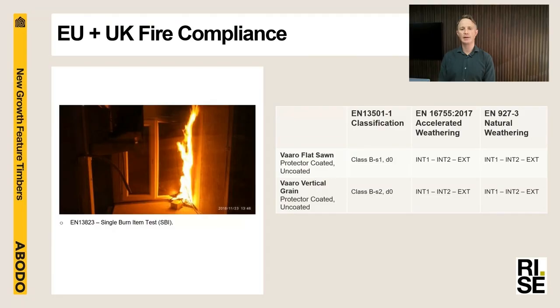For the EU and the UK, the EN 13823 single burn item test, or SBI test, was used. This is a slightly smaller scale test, 1.2 metre high wall in a corner configuration. And through this testing, we achieved Class B according to EN 13501, which is the highest classification for wood. We also achieved this classification after pre-weathering according to EN 16755. And I'll talk a bit more about that in a minute. This testing was conducted at RISE in Sweden.